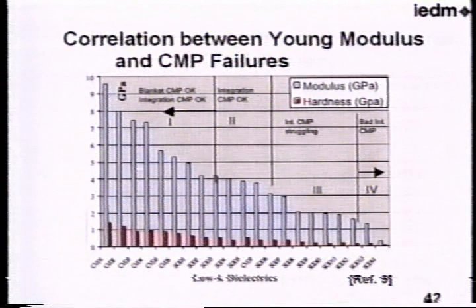This data shows the correlation between the Young Modulus and CMP failures. And this failure is strongly dependent on the sample structures, say pattern and blanket. For example, the Young Modulus is below 4 gigapascal. The test of the pattern wafer is okay, but not for a blanket. So there is some correlation between the mechanical strength and CMP failures.